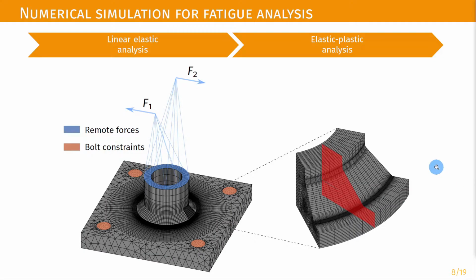Fatigue damage analysis was conducted numerically by means of a submodel analysis. A linear elastic model was firstly used to apply the correct sequence of loads and constraints, while the submodel with elastic plastic material behavior was used to obtain the structural values necessary for the calculation of damage factors. In red is highlighted the critical section of the submodel. In this section, the critical plane factors have been calculated. It was found that the weld root was a critical location for both loading conditions, so for pure bending and pure torsion.